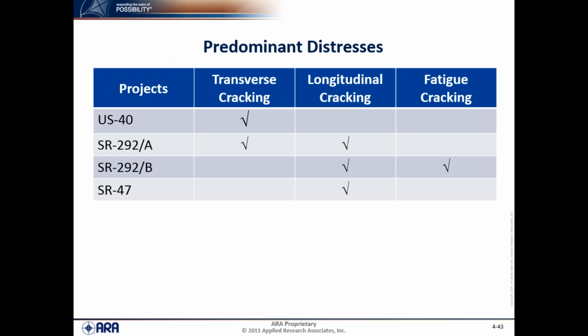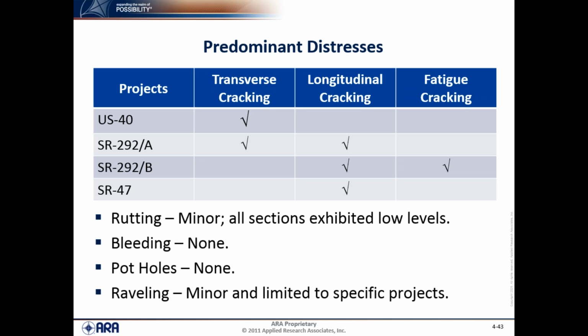So our predominant distresses: on US 40 it was transverse cracking. That's the predominant distress. Those transverse cracks are reflection cracks. On SR-292/A and B, the A was near Route 33, adjacent to it. Transverse cracks and longitudinal cracks. And we believe the longitudinal cracks here are really the early stages of the T cracking. On State Route 292B, the predominant distresses were longitudinal cracking and fatigue cracking. And then State Route 47, longitudinal cracking. We're listing that as the predominant distress, but the amount of longitudinal cracks is relatively small on that section of State Route 47.